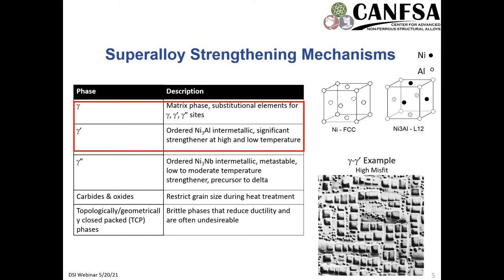In the processing conditions that we will be exploring for this, TCPs, or topologically close packed phases, are not observed, but they can occur. And these are brittle phases that reduce ductility and also consume a lot of the elements that are used for other desirable strengthening phases. So it has a twofold degradation in life, but we won't really be focusing on this. Just good to know that those do exist.